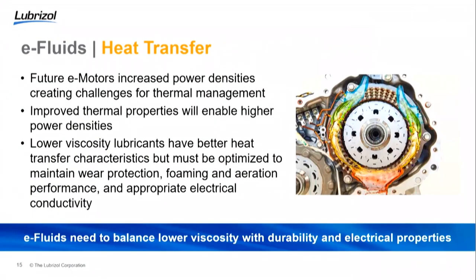And also heat transfer. So in the future, the e-motors are going to have increased power densities. So I mentioned the increased performance needs. And that can create some challenges for thermal management. The improved thermal properties of taking the heat away from the units will enable higher power densities. And that's where the lower viscosity lubricants have better heat transfer characteristics. It's really only viscosity which shifts that. To have that lower viscosity, the fluid then needs to be optimized so it maintains the wear, but also the foaming and aeration performance and the electrical conductivity, because electrical conductivity increases as viscosity decreases.